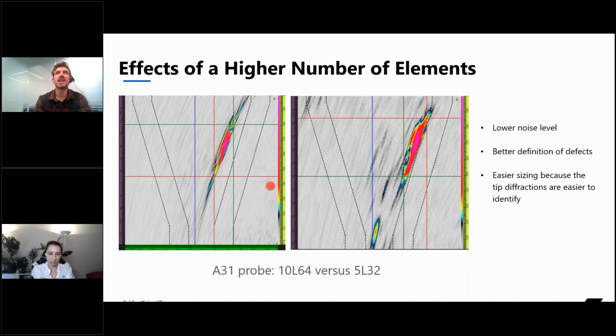Here comparing the actual number of elements. So here with an A31, slightly different probe, with a 10L64 versus a 5L32. Again, because we have 10 versus 5 megahertz for frequency, the actual resolution in the 10 megahertz image is better. But we can also see that it's harder to see the tip diffraction from our lack of fusion using the 32 element probe. There's even more noise. So this is going to be not quite as easy in order to size our actual defect. So here we have the tip diffractions, which are really obvious. With this one, we're going to have to look a bit closer to actually distinguish where our tip diffraction is.